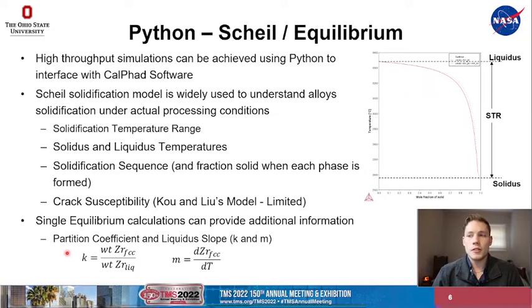So the Scheil solidification model provides a lot of information that we can use to understand the alloy's solidification under actual processing conditions. A few key parameters that we pull from the Scheil solidification curves include the solidification temperature range, as well as the liquidus and solidus temperatures, solidification sequence, and then an initial look at crack susceptibility. So Kou and Liu's model is a common model that has some limited application to crack susceptibility, primarily with aluminum alloys.